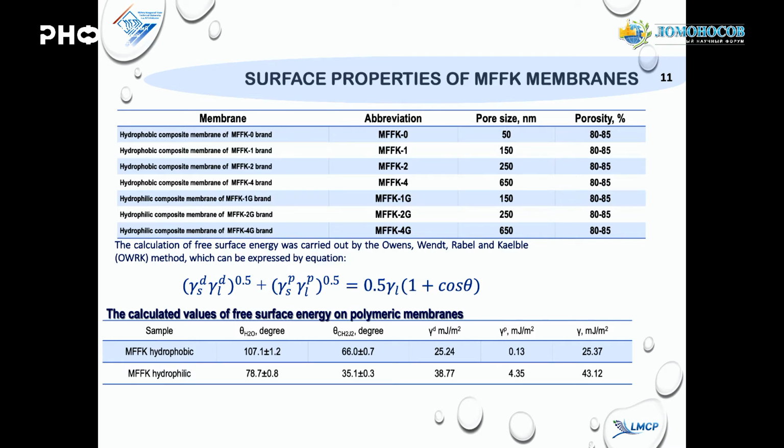It is really important in your scientific work, if you see some trends, to stabilize many parameters and try to change only one or two of them, to easily understand the nature of the things which you are investigating. In our case, we used different materials, hydrophilic and hydrophobic, with the same level of porosity, around 80–85%, and with different pore size.